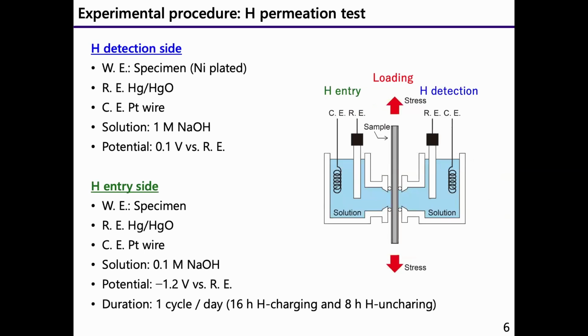Here is the experimental procedure of hydrogen permeation test. This is a schematic diagram used in this study. For the hydrogen detection side, the working electrode was specimen with nickel plating. Reference electrode was mercury oxide electrode. Counter electrode was platinum wire. The cell was filled with 1 molar sodium hydroxide aqueous solution, and specimen was polarized at 0.1 volt versus reference electrode. For hydrogen entry side, the working electrode was specimen.